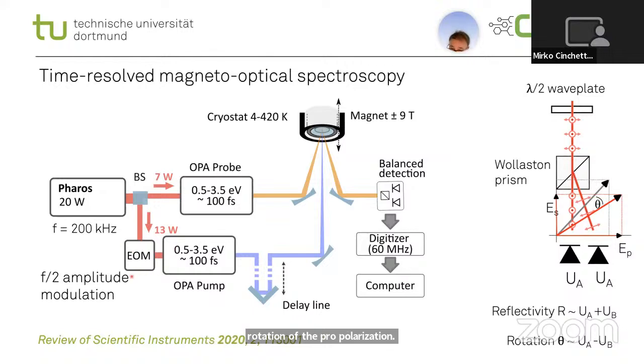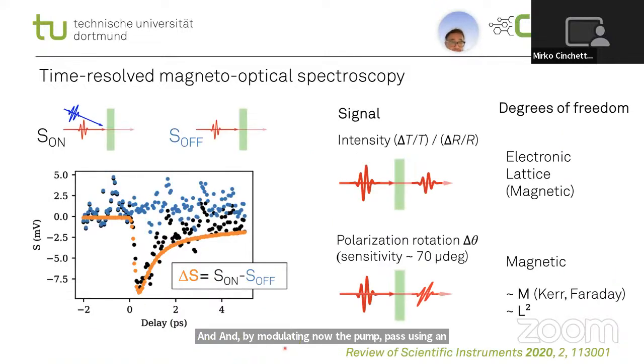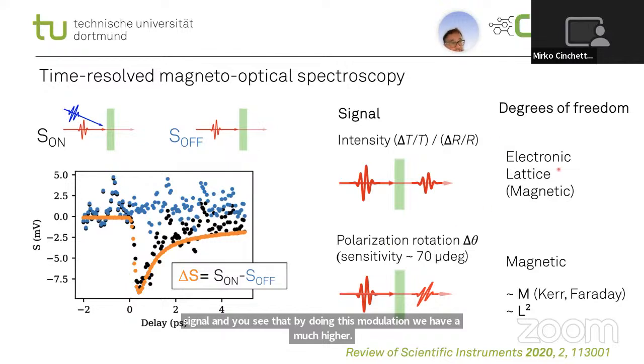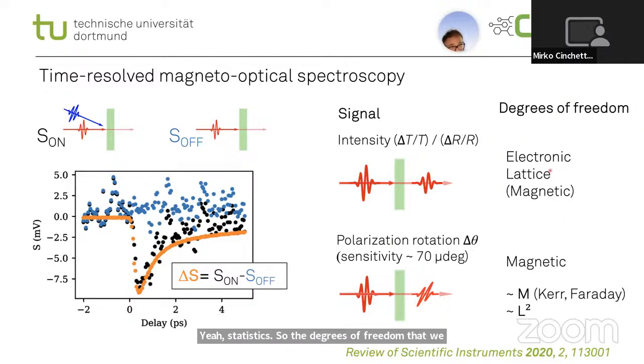By modulating the pump pulse using an electro-optical modulator, we can also achieve high sensitivity in the measurement of the polarization rotation. We achieve here a sensitivity of about 70 microdegrees. And here you see the modulated and unmodulated signal, and you see that by doing this modulation, we have much higher statistics. The degrees of freedom that we measure, I already mentioned: electronic and lattice by measuring transient reflectivity. And of course, if you want magnetic information, typically you also measure the rotation of the polarization of the probe beam.